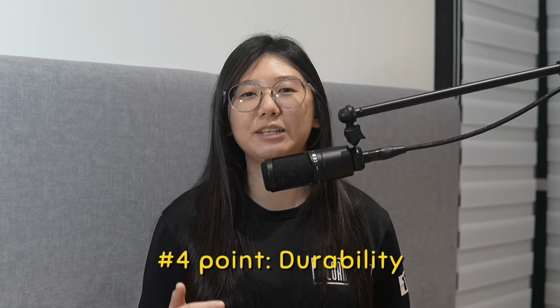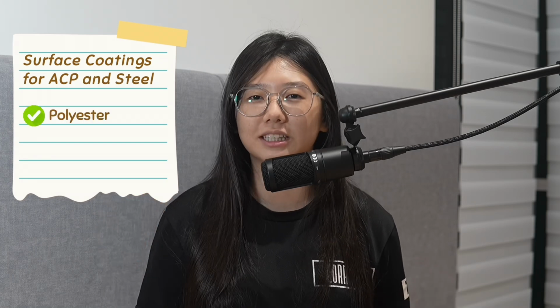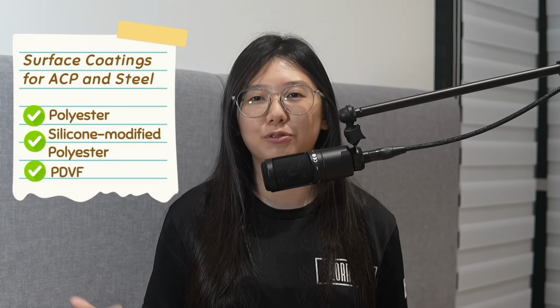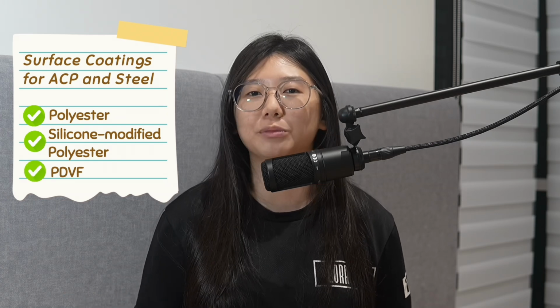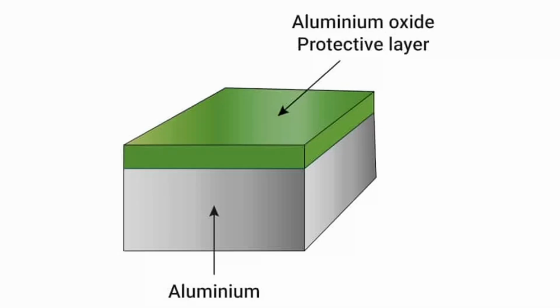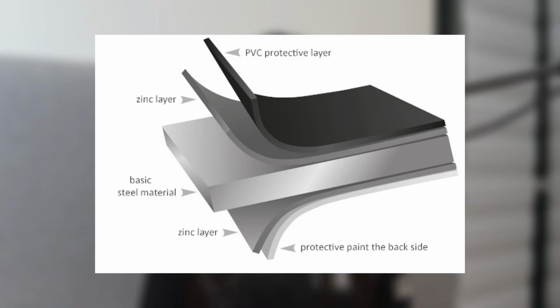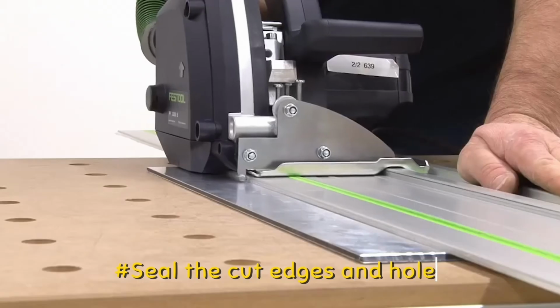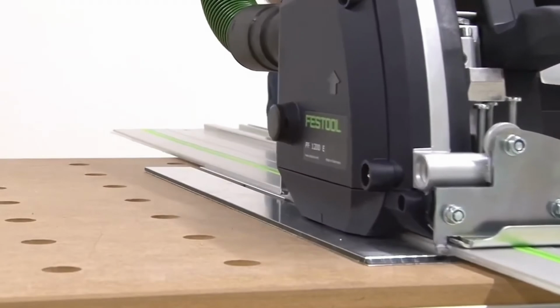Both coated steel sheets and the ACP can be applied with different coatings such as polyester, silicone modified polyester, and PVDF to protect the base metal from weathering such as from the rain or from the sunlight's UV. In general, aluminium exhibits better corrosion resistance than steel due to its natural formation of a protective oxide layer. Hence, bare aluminium exhibits a low corrosion rate, typically less than 1 micron per year in atmospheric conditions, while steel is about 8 microns per year. To counter corrosion, the steel sheets are galvanized with an aluminium and zinc layer on both sides. This is why manufacturers would urge builders to seal cut edges and holes using the correct cold cutting tools and apply fasteners with rubber washers.